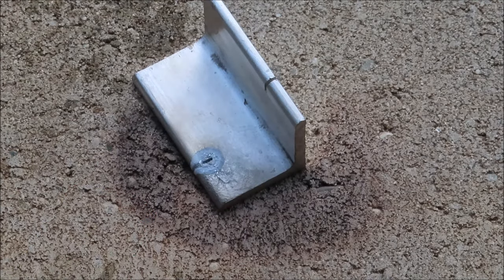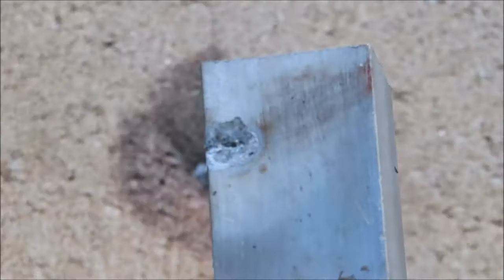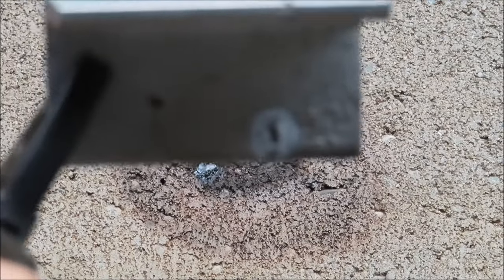Okay, spraying water on it did not work. All right, well that didn't work. It says to heat them up to roughly 600 degrees Fahrenheit, and I only got to about barely 400, and the aluminum started to deform. The rod did melt, but squirting water on it did not help. Let's go ahead and try it again on the other side. It did seal it all the way through, but when I sprayed the water on it, it created a bit of a hole there, so I'm not going to do the water this next time around.